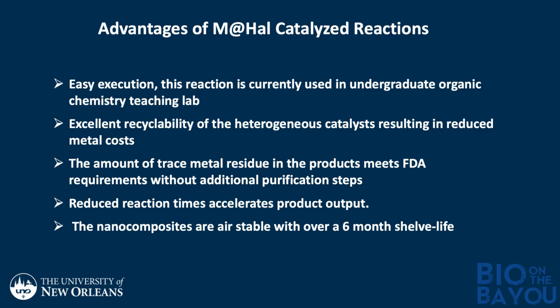So the advantages of our systems, basically, they're easy to execute. A lot of these catalysts we're using currently in my organic labs with my students. We use this in one of the teaching labs for them to do it. They can handle it easily. We get excellent recyclability, and essentially the amount of trace metal is very low, in the sense the halloysite tends to hold on to the metal, and reaction times are very short, accelerating throughput. Now, we haven't done this on large scale yet, but we can set up 10 reactions right next to each other and make 20 grams of material in an hour. And last but not least, these nanocomposites have a long shelf life. They're air stable. You don't have to work in a glove box to load catalysts, and so they're very convenient in that way.